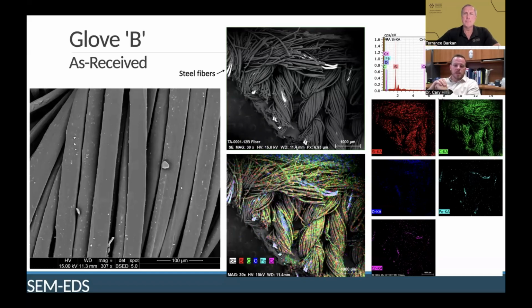And then we perform our elemental analysis, and you can see that there's iron, there's chromium present, there's steel. So there's steel fibers, steel additives. There's also high silica content, silicon and oxygen overlapped, so silicon dioxide. These are traditional cut-resistant additives, which are fine to have in a glove. There's no need to only use graphene, but all this is to point out that these are the cut-resistant additives that we were observing in this glove, with steel fibers along with silicon dioxide embedded within the fibers themselves.